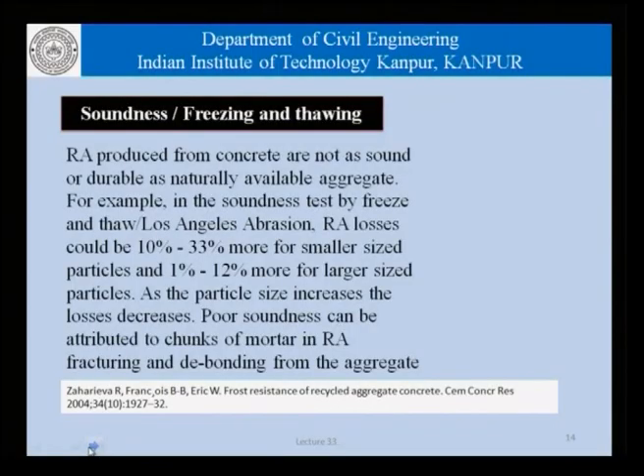Now, let us come to soundness and freezing and thawing of the recycled aggregates. Recycled aggregates produced from concrete are not as sound or durable as naturally available aggregate. For example, in the soundness test by freezing and thawing or the Los Angeles abrasion tests, the recycled aggregate losses could be 10% to 33% more for smaller sized particles and 1% to 12% more for larger sized particles. As the particle size increases, the losses decrease. Poor soundness can also be attributed to chunks of mortar in recycled aggregates fracturing and debonding from the aggregate.